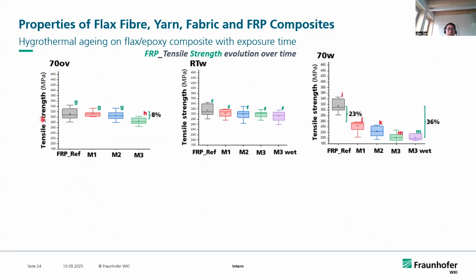The left figure gives the flax FRP composite tensile strength exposed to the 70-degree oven condition. As you can see, compared with the reference samples, after 3 months there was only a small reduction in the tensile strength, 8%. For the flax epoxy composites in room temperature water, compared with the reference, after 3 weeks the reduction is also very small. But when we exposed the flax FRP composites to 70-degree water conditions, even in the first month we can see a 23% drop in the tensile strength. After 3 months, further reductions were also observed.